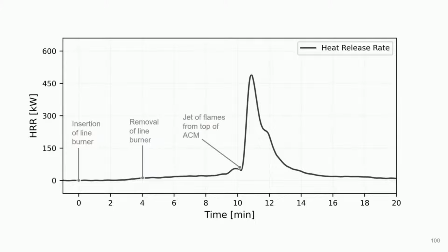The fire will then steadily grow during the course of about 6 minutes, and we'll then observe a jet of flames from the top of the Renabond PE rain screen from about 10 minutes into this particular experiment. Shortly after this, we'll observe, if we look very closely, separation of the inside aluminium skin of the Renabond PE, resulting in a very rapid and violent escalation of burning. And this is what I refer to as escalation to full involvement of the ACM in my Work Package 2 report.